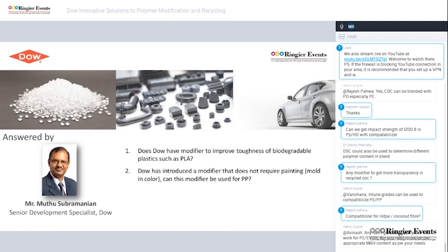For PP, you can also try the same concept to improve the scratch resistance, but the issue is PP has poor compatibility with Surlyn. So we need to use a compatibilizer such as maleic anhydride grafted PP to improve the compatibility between PP and Surlyn. This may enable better scratch resistance, but whether it will have a higher glossy appearance and mold-in color, this is something we still need to validate.